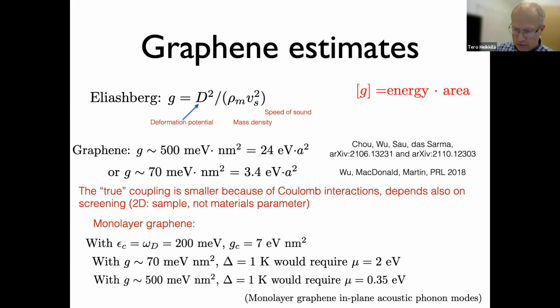Okay, now we want to describe graphene. So we can ask, how large would be an electron-phonon coupling, say, the attractive interaction that you would get from electron-phonon coupling. There have been a few estimates in the literature. Actually, in all these papers there is one same author, which is Feng-Ching Wu, but the papers contain different sizes of the coupling constant. I show this here to show that this thing exists, and you can estimate it based on quantifiable things like deformation potential, mass density, speed of sound.